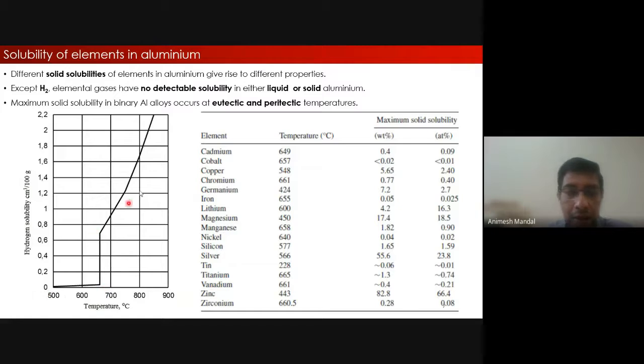That means, if you do not remove this hydrogen before you cast this liquid aluminum metal into your molds, you're going to end up with different kinds of defects related to porosity, blowholes, wormholes, so many kinds of defects. That's why hydrogen is quite undesirable in your aluminum alloy. So you need to find a way by which you should be able to drive out this hydrogen from your molten aluminum. That's very, very important. That's one of the key things when we talk about melting and casting of aluminum alloy. So that has to be kept in mind.